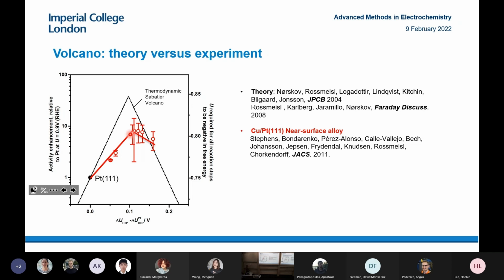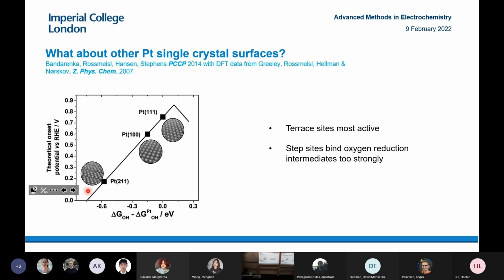So of course, you could argue this is just from our study. What about if we looked at other studies on platinum single crystals? What happens if we look at a simple platinum 111 single crystal? What happens if we look at other surfaces, more open surfaces? Generally, when you have undercoordinated sites, they tend to bind a lot stronger to reaction intermediates. So let's say if you look at platinum 211, the step site, what we find is that the theoretical overpotential is a lot larger. You'd expect much lower activity for oxygen reduction on the step sites than platinum 111.